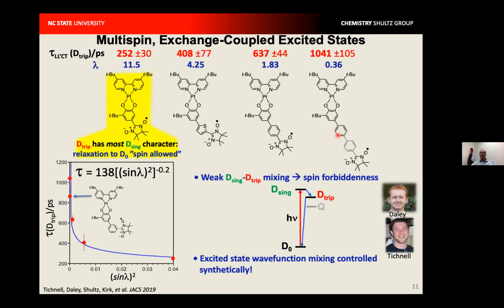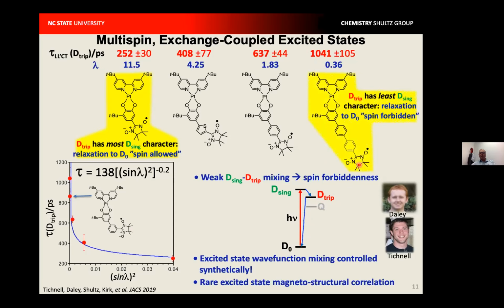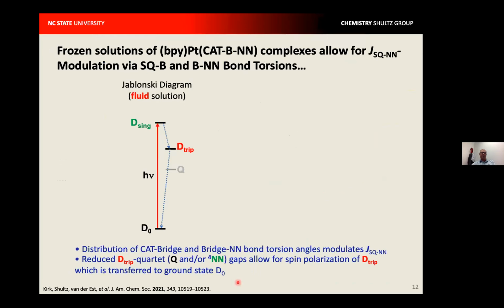With longer bridges, or bridges that cause weaker coupling in the excited state, D-trip has very little D-sing character, and there's an amount of spin forbiddenness built into the non-radiative decay back down to the ground state. So you get longer excited state lifetimes when you have weak magnetic exchange in the excited state. So that was a rather rare example of a magnetostructural correlation for these types of molecules.